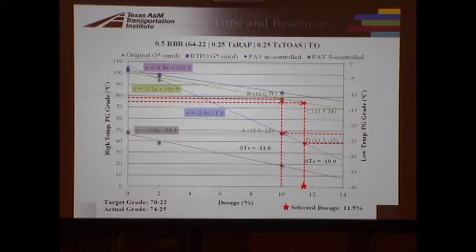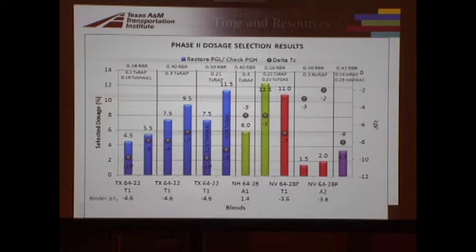Now, what is the value of this delta TC thing? So the delta TC has been shown to be tied to some age-related cracking at airports, and some people have suggested a value of minus 5 is sort of, you don't want to get more negative than minus 5 after 40 hours of PAV aging. Of course, this is after 20 hours of PAV aging. So 40 hours of PAV aging, it's like, forget that. That's just way too high in terms of a dosage. And we also don't know really if that minus 5 is the right threshold or not. So for right now, we're just kind of keeping track of those delta TC values.